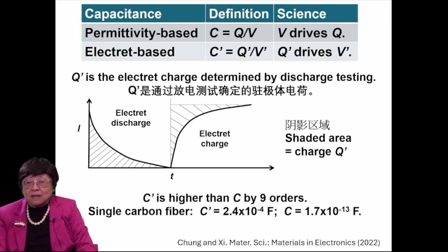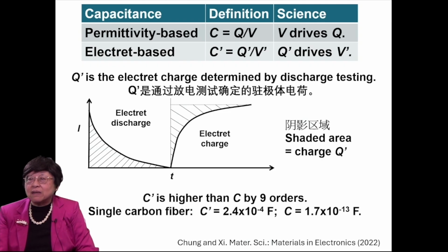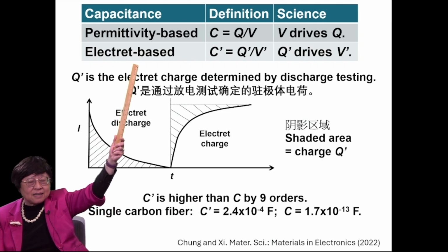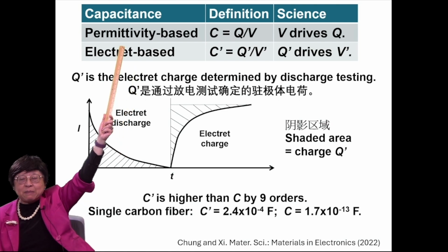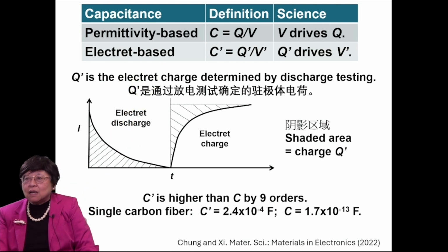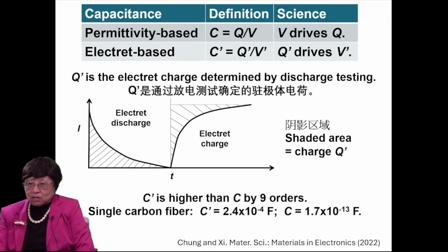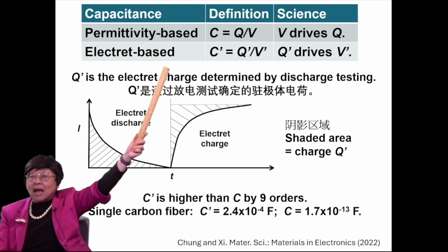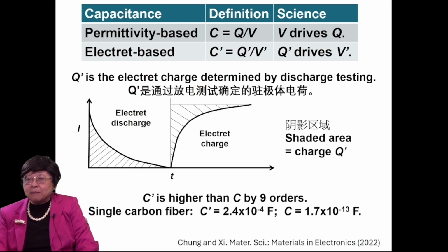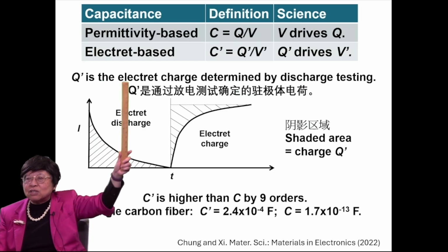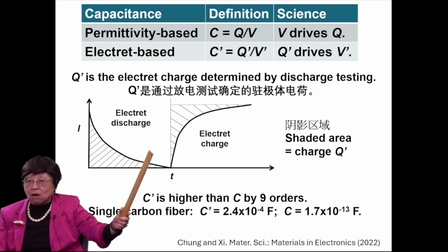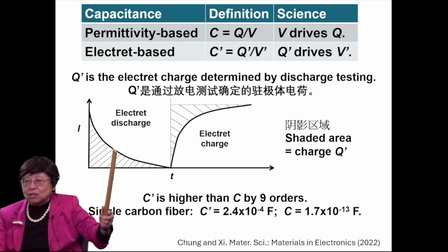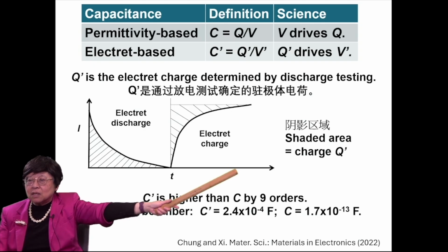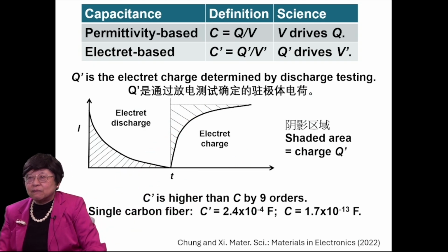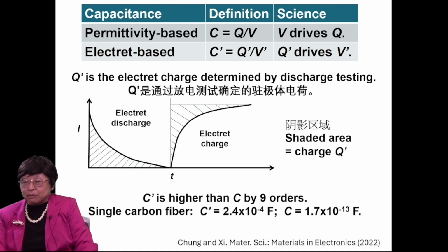However, in the case of the electrets, I introduce a new scientific quantity, which I call electret-based capacitance. The conventional is the permittivity-based capacitance, C, which is defined as Q over V, with V, the voltage, driving Q, the charge, on each plate. But the electret-based capacitance, I define as C prime, which is Q prime divided by V prime. Q prime is the electret charge, which is determined by discharge testing. This current versus time during discharge, the area under the curve gives you the charge Q prime. And V prime is the electret voltage. And Q prime drives V prime.